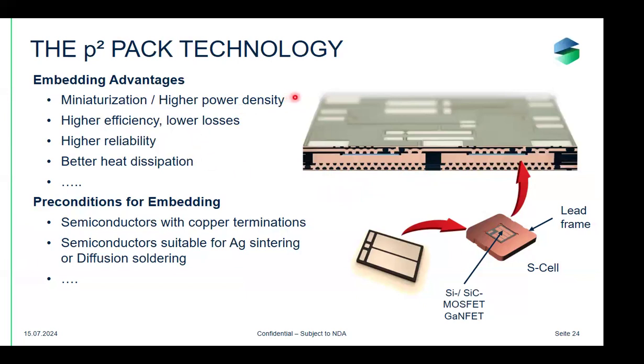So when we started, we looked at miniaturization of power electronics. This was the first driver of this technology, and still it's valid because today everybody looks to get higher power density in this application. But what we also learned by making these samples and testing them is that we could create a higher efficiency in switching. So we could create lower losses, especially in the switching. Lower switching losses, and for low voltage applications, also lower conduction losses, because by replacing the bond wires that you typically have in a package by these copper-filled microvias, we could also lower the RDS on, the residual RDS on of the total device, which can be seen from the data sheet.